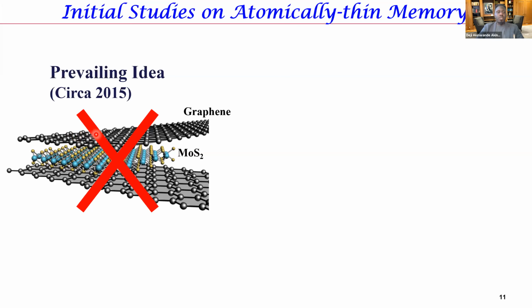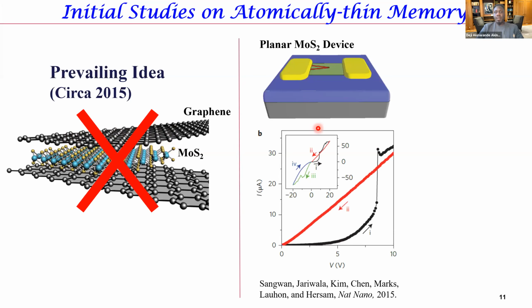And the popular opinion was that, just like in metal oxides, there was a lot of suspicion that the current leakage through this very, very thin 2D material will be excessive and this would not work. Indeed, the only paper at that time was by my very esteemed colleague at Northwestern, Professor Mark Hersam, where he showed a lateral device, so a planar device.